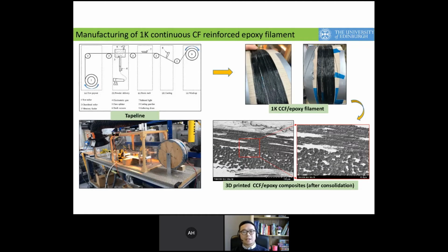First, the carbon fiber reinforced epoxy filament is manufactured using a tape line previously developed by Cranfield. Cranfield has already introduced the tape line, so I'm not going to repeat that. As the filament is quite small, we use infrared heating instead of dual contact heating, which is quite effective to produce filament with a good circular cross-section.